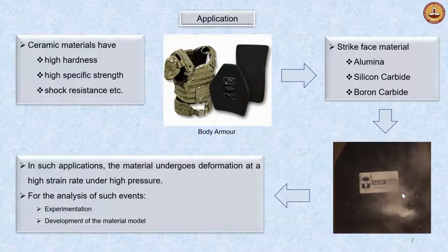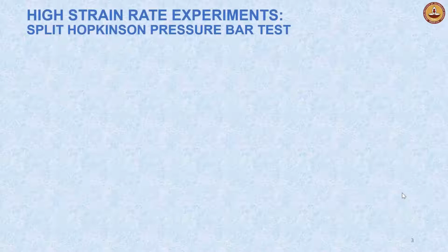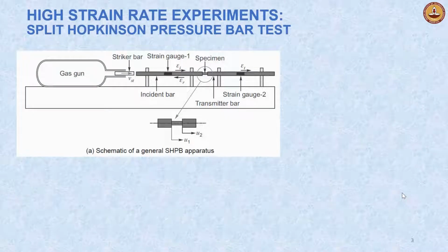Split Hopkinson pressure bar, or SHPB, test is used for high strain rate experiments. SHPB works based on one-dimensional wave propagation theory. Strain gauges were pasted on the incident bar and transmitted bar to capture incident, reflected, and transmitted pulses generated due to the wave propagation through the bar and specimen. These pulses are post-processed to get the stress strain curve at a different strain rate.